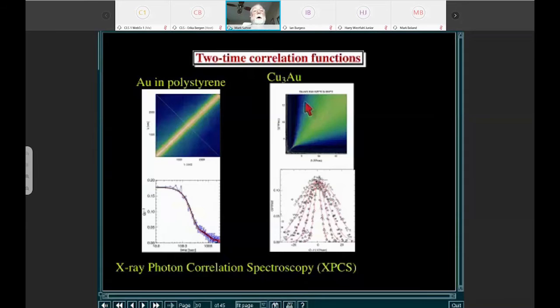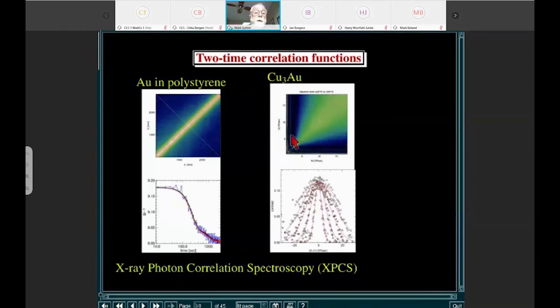But in copper-3 gold, what we did is we quenched the sample through a phase transition, and so now the new ordered phases are growing in domain size, and so the scattering is now changing in time. But if we were to normalize by the instantaneous average, so in some sense we average away the speckle in a single pattern, we get a diffraction pattern, which is like incoherent scattering, and then we can look at how that changes in time, and now we can see that the two-time correlation function is no longer constant along the diagonals. As a matter of fact, we can see that in the system, the fluctuation times are growing as a function of time. And if we take various cross-sections, we can go through that.